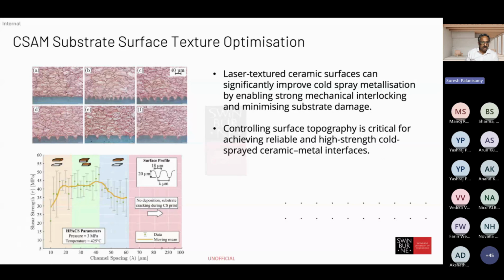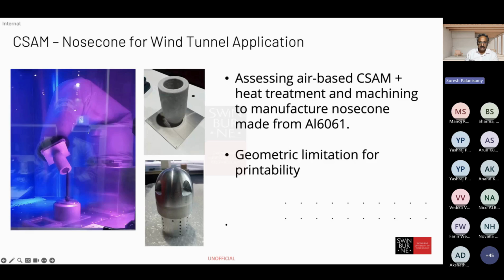And again, this work was mainly focused on the interface substrate, how the interface bonding or surface bonding can happen with the ceramic tiles with the interlocking mechanism. As you can see here, with the different interlocking mechanism, you can get a better bond strength. And at a particular condition, it achieves far more strength compared to other processes. The most important thing is that all these studies are vital for us to understand what properties it might achieve during the cold spray process.